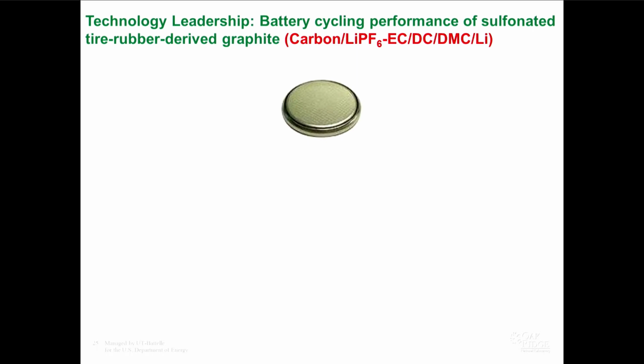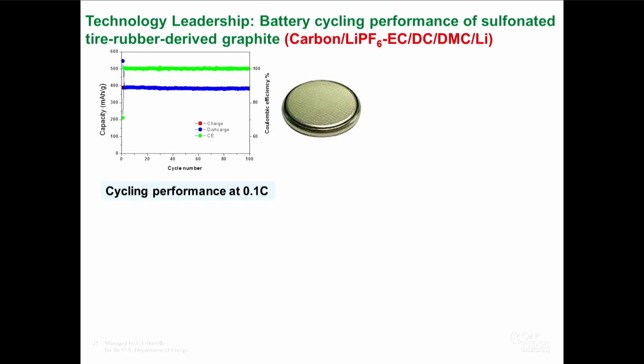So this is the extra step we developed at Oak Ridge, go through the acid treatment and then pyrolyze and make the graphite powder. It's the same half cell configuration. And if you look at the performance, the Coulombic efficiency, the green one, you need to be close to 100, so we are very close to 99.9. And the discharge capacity, you can see the first capacity is high, then it drops down to like 390 to 400 range, and it's constant over 100 cycles. So we have shown a performance of our sulfonated tire-derived graphite for 100 cycles in the coin cell configuration.